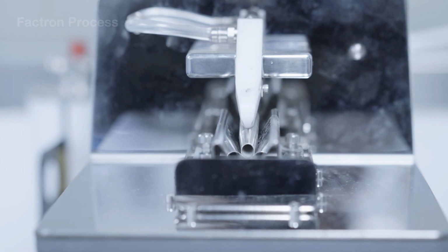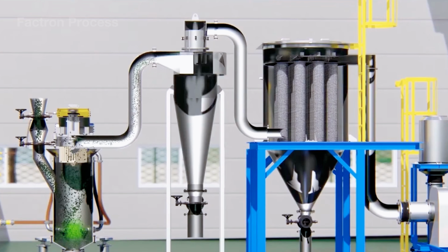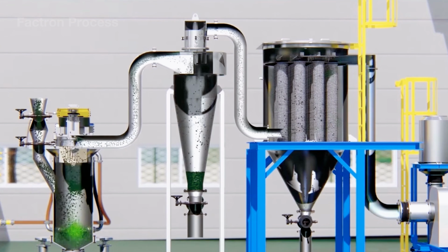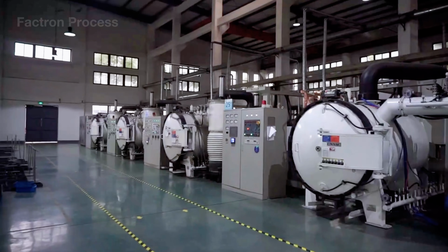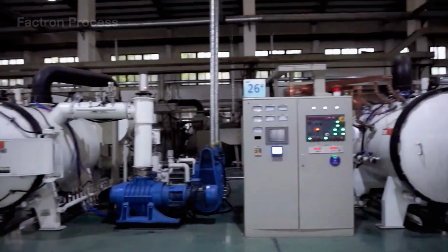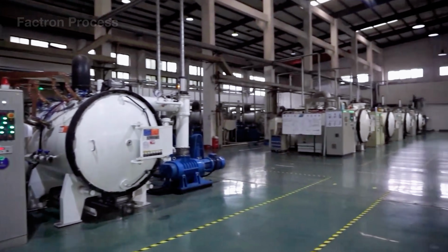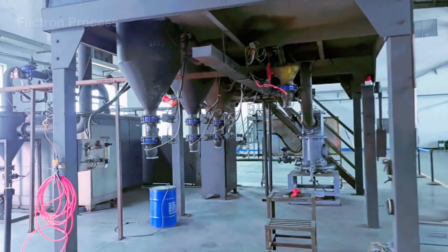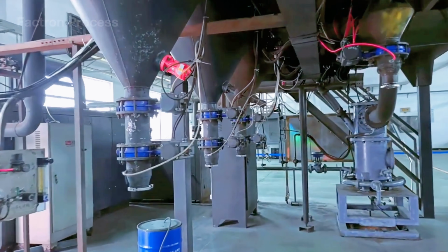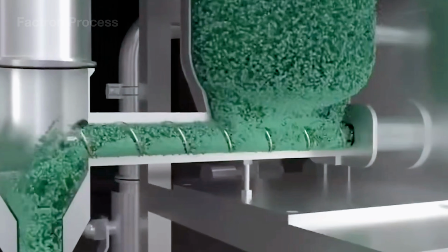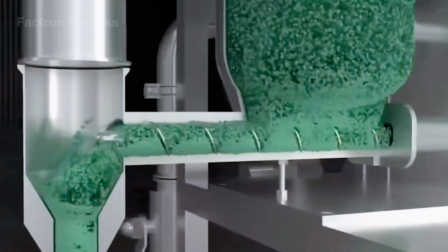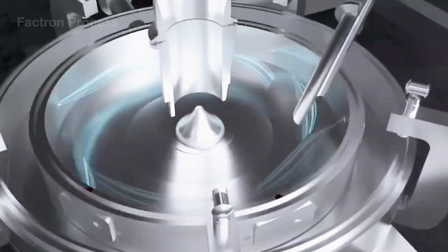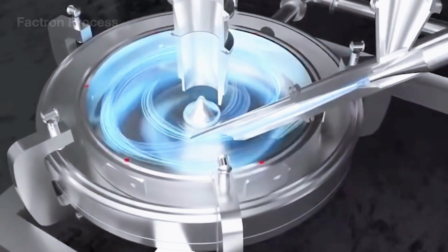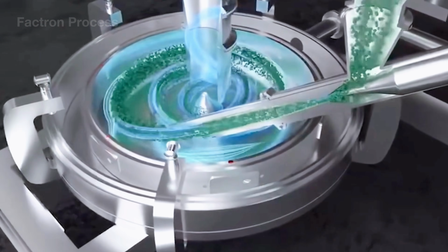The material is then transferred into a jet mill to reduce the coarse particles into ultrafine powder. Inert gas is blown through Laval nozzles at a supersonic speed of Mach 2, twice the speed of sound. The particles collide directly with one another and fracture into an ultrafine size range of 3 to 5 micrometers. At this stage, the fine powder is extremely reactive and can spontaneously ignite in air, so the entire system must remain flooded with inert gas and completely free of oxygen to prevent a dust explosion disaster.